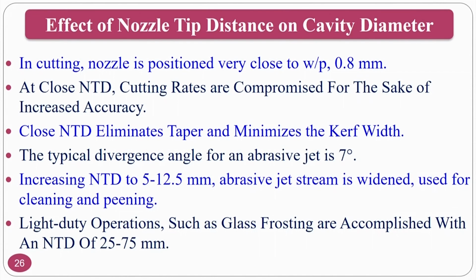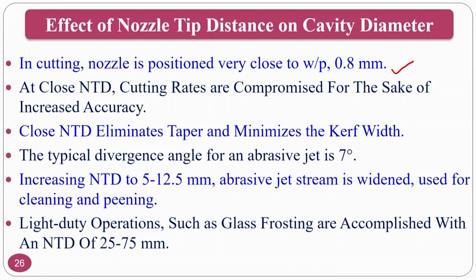Effect of nozzle tip distance on the cavity diameter. With the cutting nozzle positioned very close to the workpiece, normally the distance is 0.8 mm. At the close nozzle tip distance, cutting rates are compromised for the sake of increasing accuracy. That means that whenever the nozzle tip distance is low, your interest is to get the perfect cut or the accurate dimensions that you want. A small nozzle tip distance eliminates the taper and minimizes the kerf width. The typical divergence angle normally will be 7 degrees for abrasive jet.